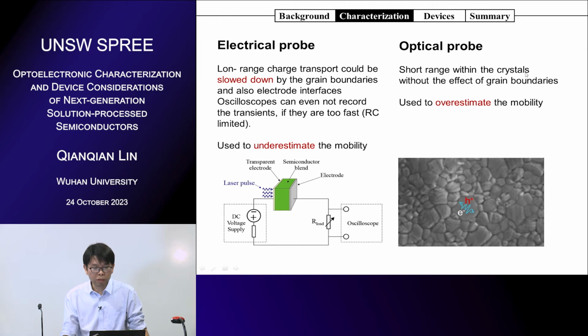And if you use optical probes, normally you will overestimate the mobility because the photons normally interact with the semiconductor within a very short probing length for the terahertz. So if you use optical methods, sometimes you will get a little bit higher mobility, or overestimate the mobility of multi-crystalline films, because you do not consider too much about the boundaries. So this is a comparison of these two methods.